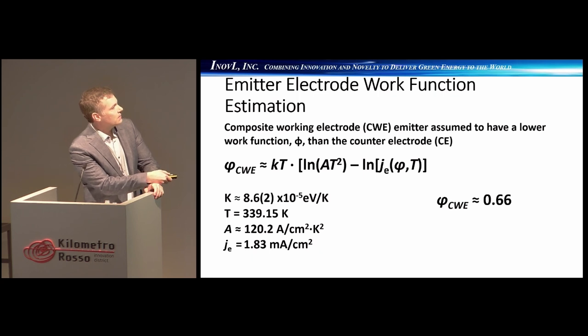All right, next one. As I said in the previous slide, we mentioned that the work function of the composite electrode is actually going to be lower than the counter electrode. And so here's just a quick calculation of the estimated work function of the composite electrode when it's active. And indeed, when you use our numbers from our current, we get a work function of 0.66 from the emitting electrode. And we get a current density of 1.83 milliamps per centimeter squared.